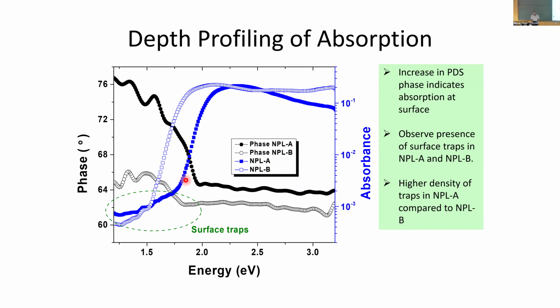Usually when the absorption is coming only from the bulk, the phase remains constant because the heat diffusion is the same for reactions that happen, since it diffuses all the way from the bulk, it has the same sort of phase constant.